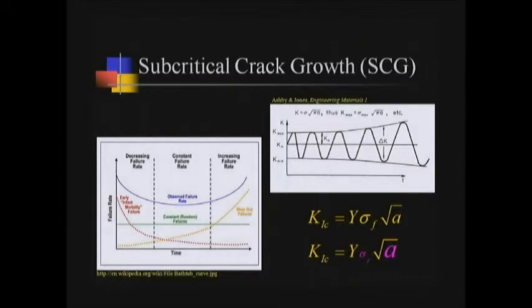But at the same time, these cracks are growing in the material, increasing the stress intensity factor, and the material begins to wear out, and more of the restorations will fail due to the growing cracks over time. And when we add those two sources of failure together, we get this blue curve. This is the observed failure rate over time, and that's what we call the bathtub distribution.